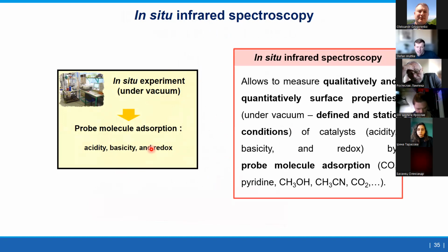So you can also measure how much you have of certain things, if you know the extinction coefficient, because we have the Lambert-Beer law. It's a very basic principle, but I want to show you how powerful these basic principles are. And then you can have a defined static condition, and then you can measure acidity, basicity with probe molecules. And the idea with these probe molecules, look, for example, CO, we will have this in a moment, they vibrate. And if they're interacting with your catalyst, they will change the vibration. And this change you use to understand it. So this is basically your magnifying glass, your probe. Sherlock Holmes had this magnifying glass to try to understand. And for us, it's IR.